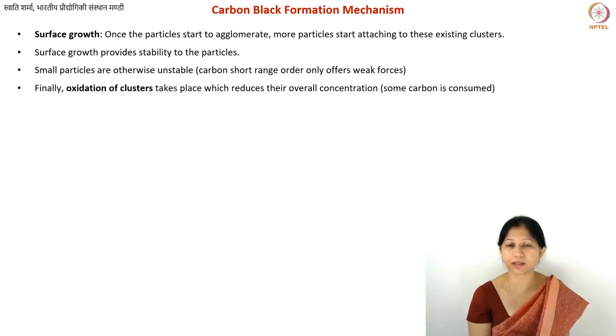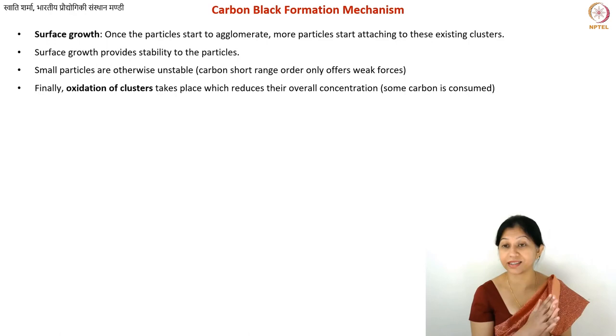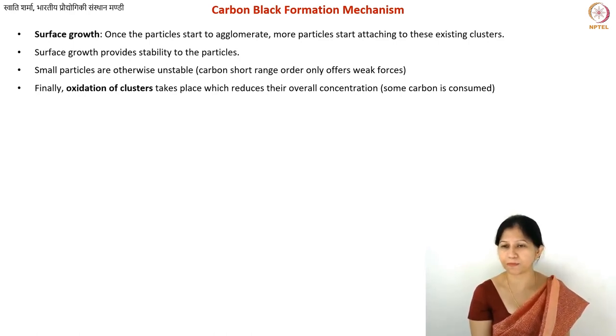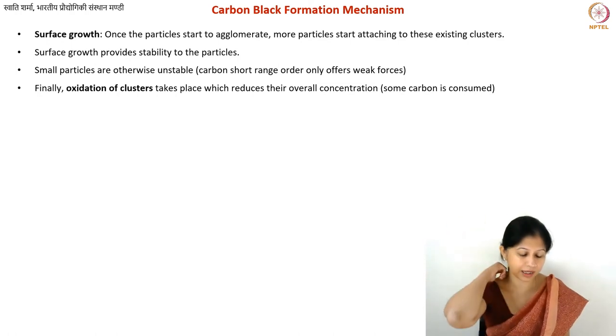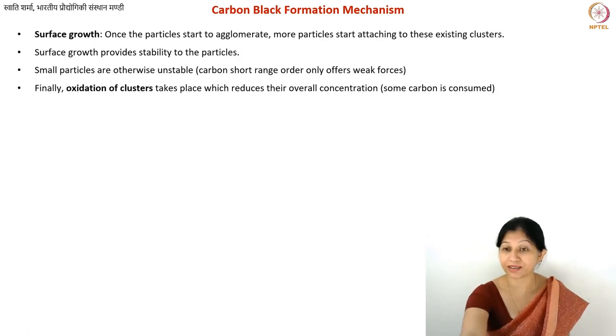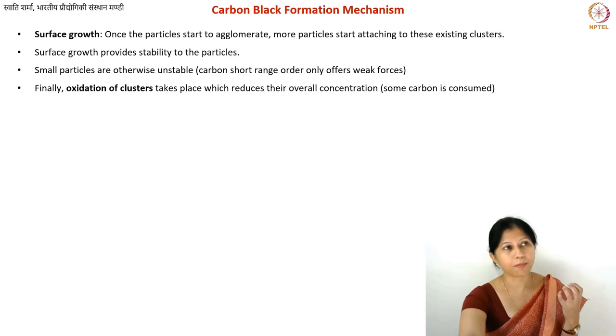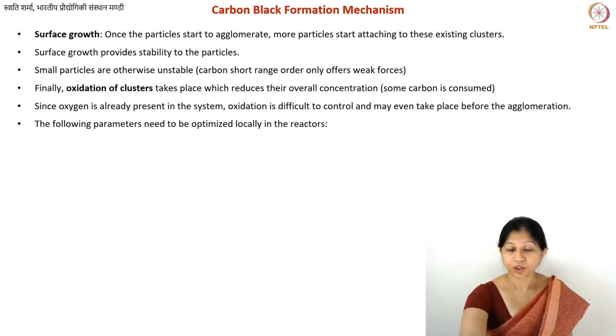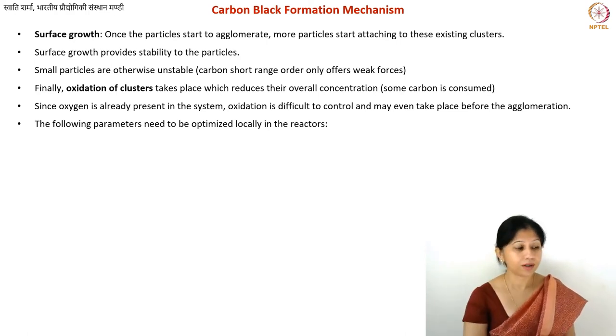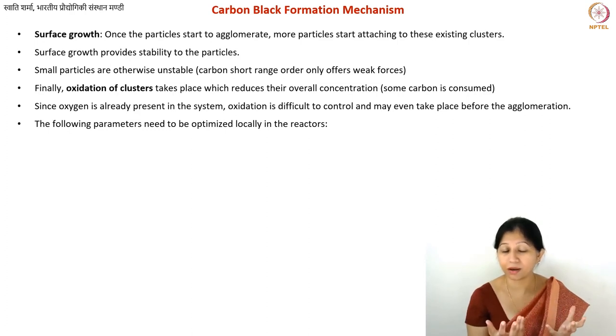Summarizing the optimization parameters: temperature is important at every step — the reactor is typically between 1300 and 1500 degrees Celsius. Oxygen concentration must be controlled, otherwise it will burn particles completely and result in something more like soot. The flow rate of gases also needs to be controlled, along with the concentration of your fuel species — oil or otherwise. Both carbon-to-hydrogen and carbon-to-oxygen ratios need to be well controlled. If there is too much fuel, you may get larger droplets of liquid hydrocarbons that form soot rather than carbon black.